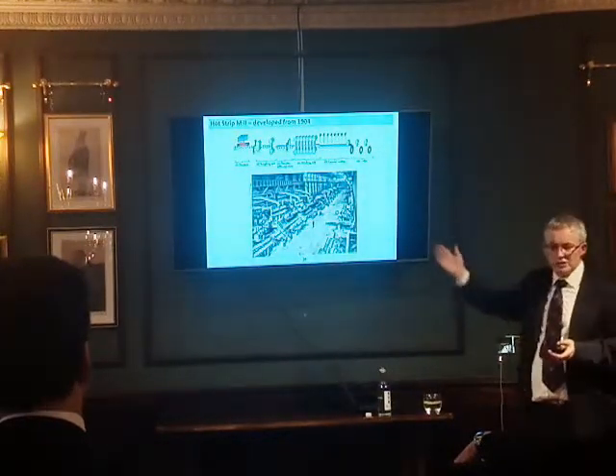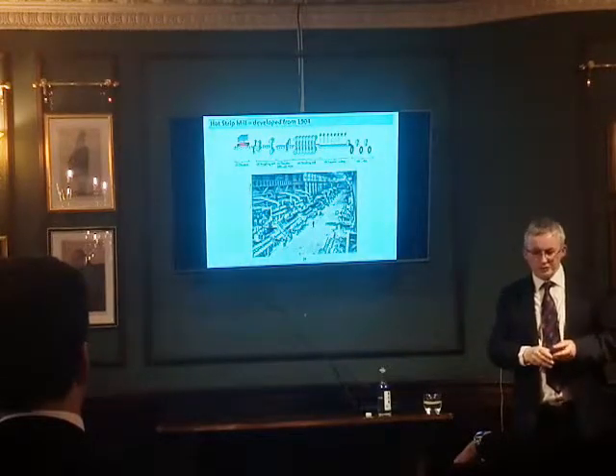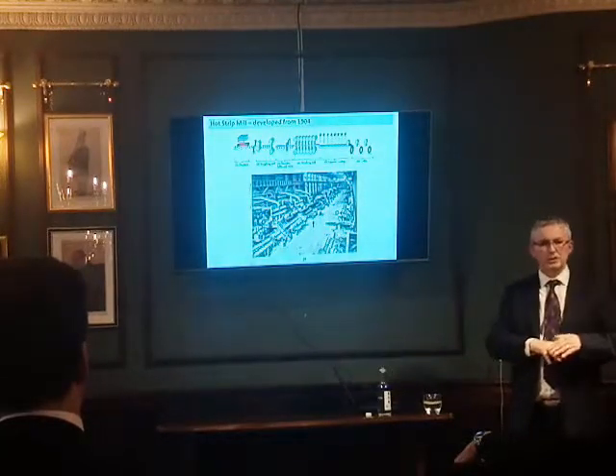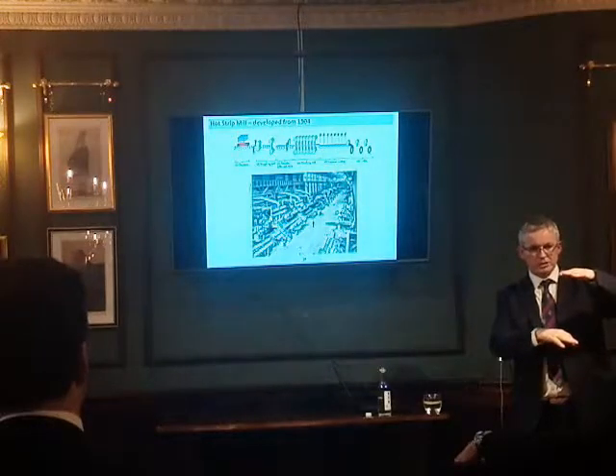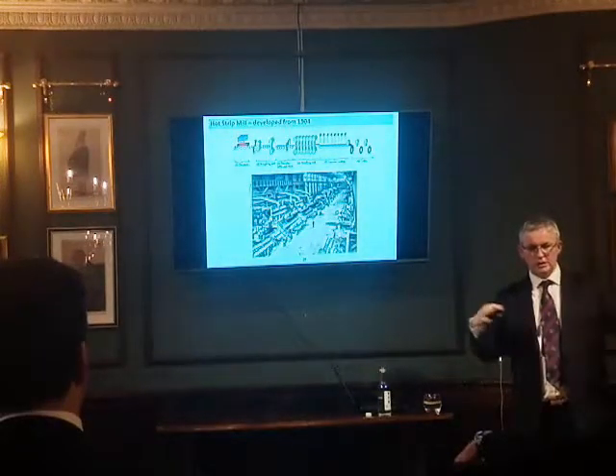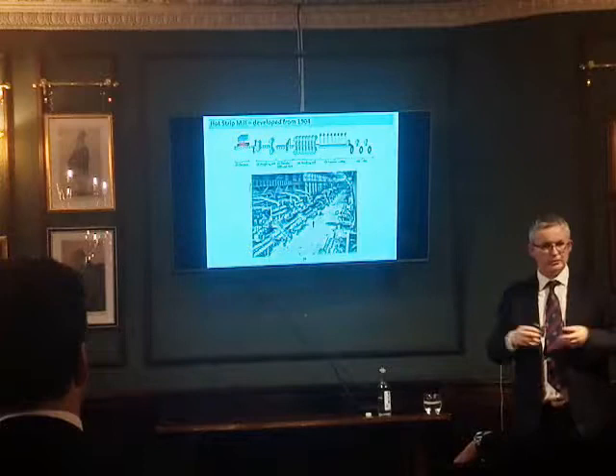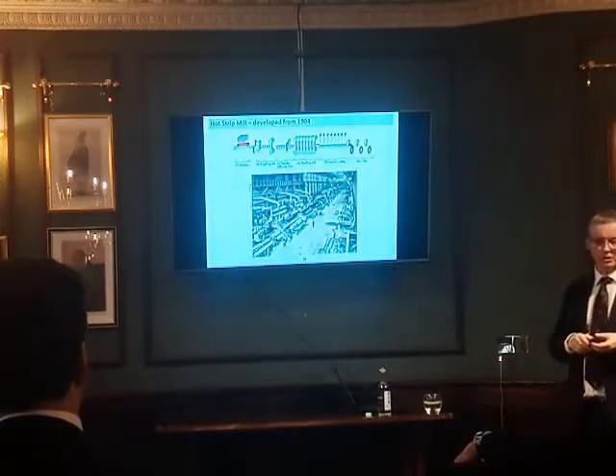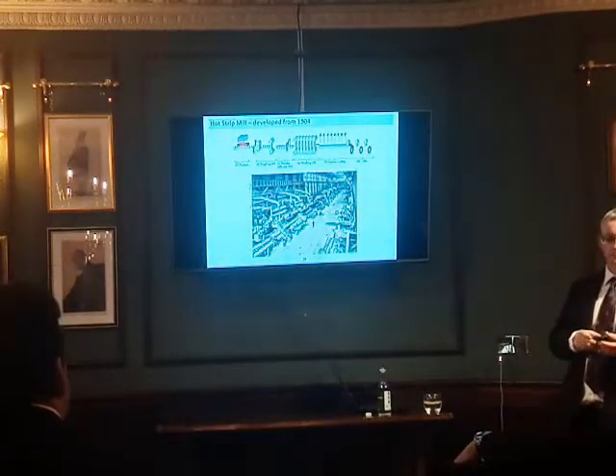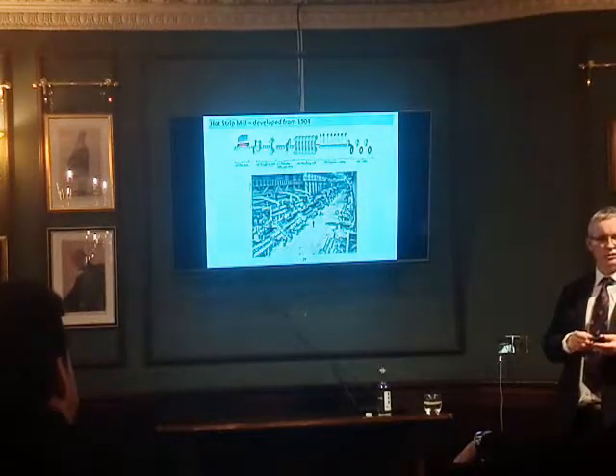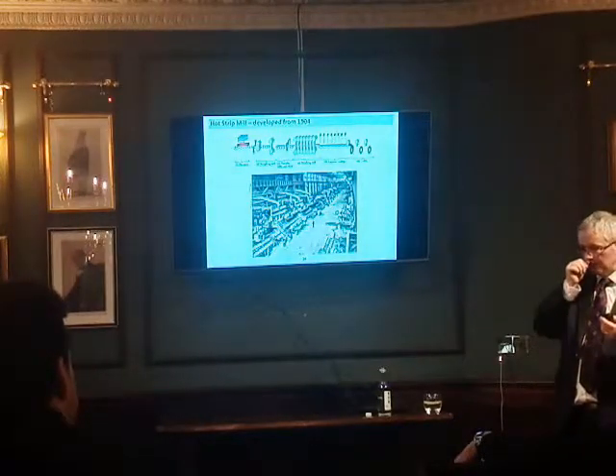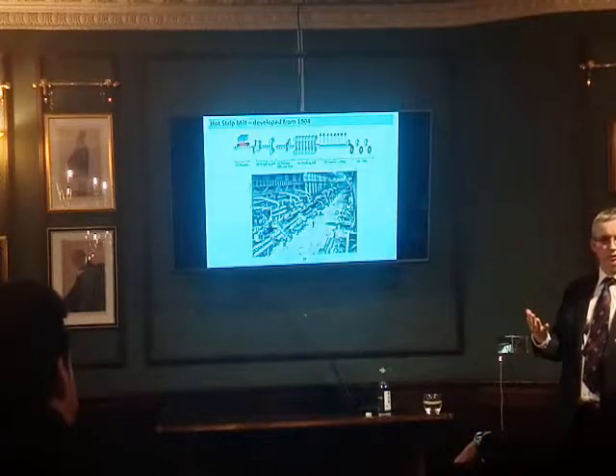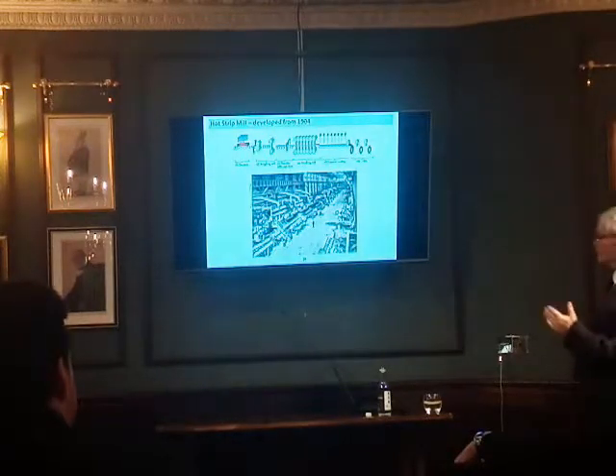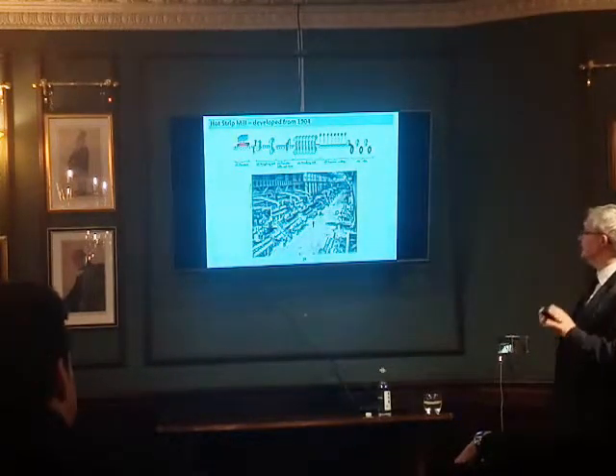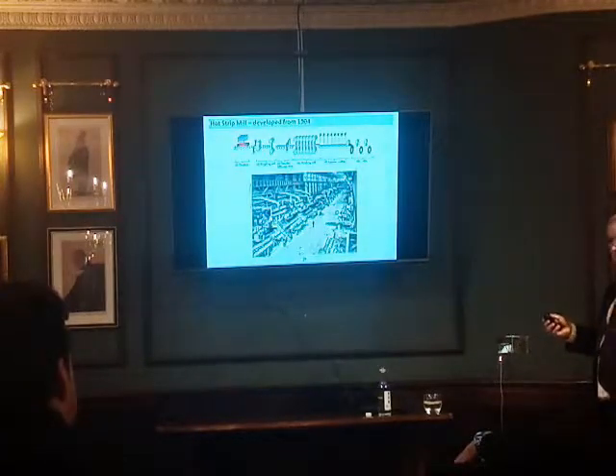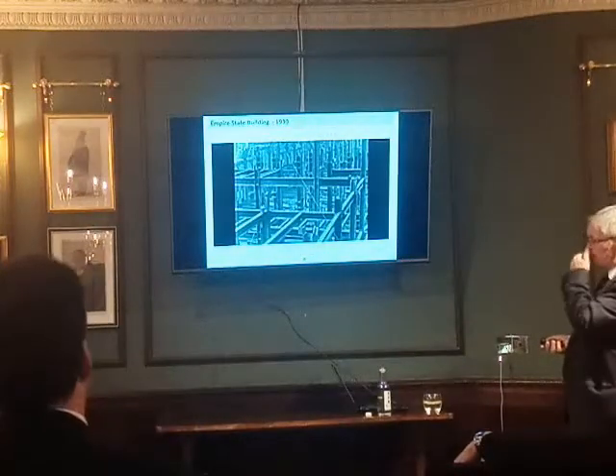And the scale of that, when you're starting, even with a modern hot strip mill, the slab is typically 25-30 centimetres thick, a metre wide, maybe 10 or 12 metres long. The largest slabs these days, some of the Russian steel plants have got slabs that weigh 50-60 tonnes. So you need massive equipment, huge capital costs. Of course, that didn't all happen straight away. I'm not saying all that happened in 1900, but massive scale to these downstream processing operations.